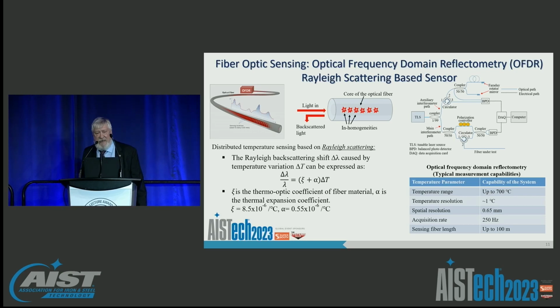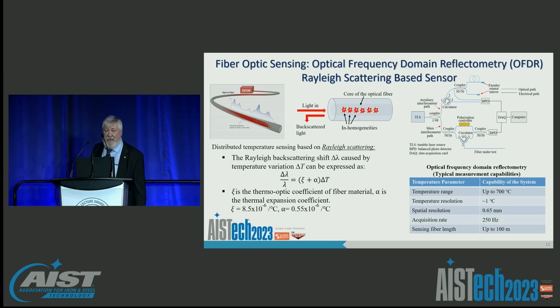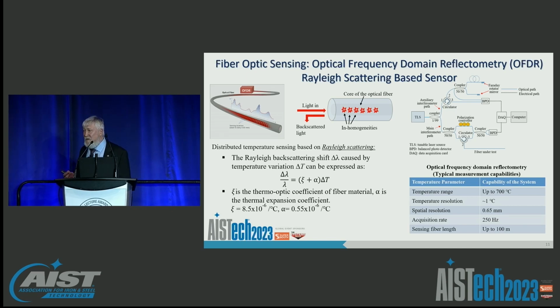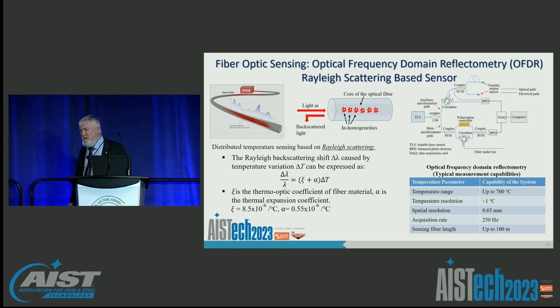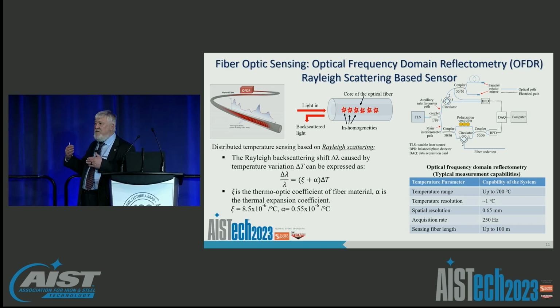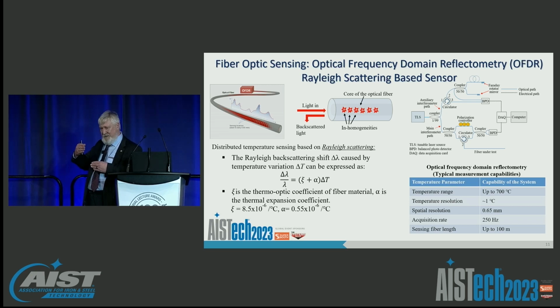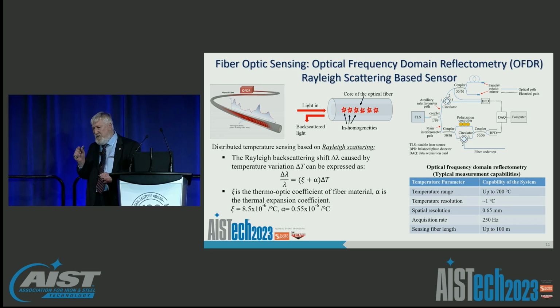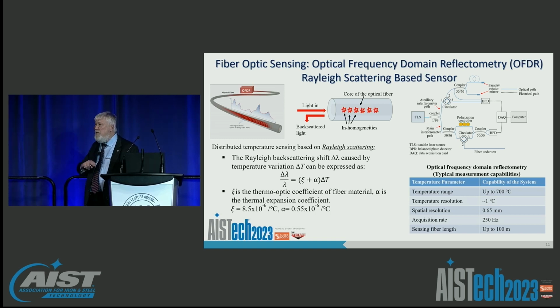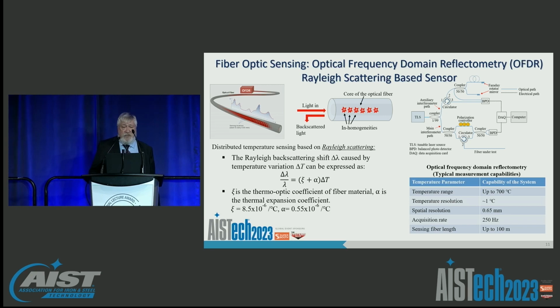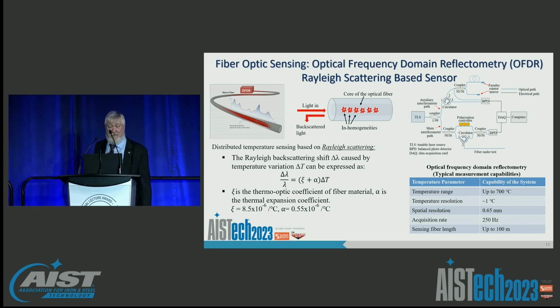This is the Rayleigh scattering, and this optical frequency domain reflectometry actually is based on these inhomogeneities within the core of the fiber. And as a result, if we interrogate that fiber and collect the Rayleigh scattering signal in a back reflection, we can get a particular spectrum that is distinctly associated with each section of the fiber. When the conditions at that location on the fiber change, that pattern remains but shifts in its frequency. And so we can use cross-correlation methods to actually interrogate about a 0.5 millimeter space along the length of the fiber. And that leads to what is essentially a near continuous temperature measurement. And this just shows some of the interrogation systems that are used to collect that and some of the fundamentals behind it.